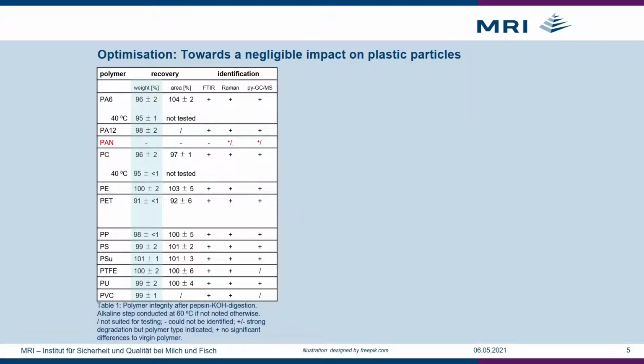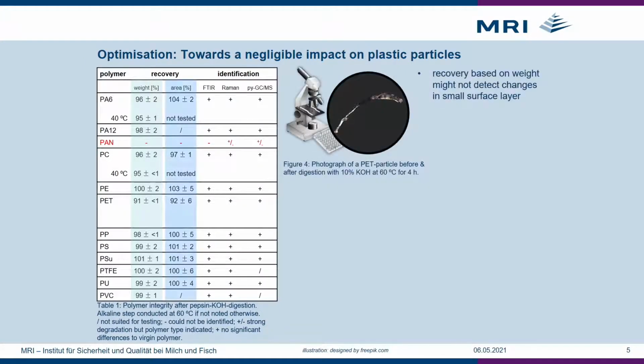First of all, we addressed polymer integrity, so we checked the recovery of polymer mass after enzymatic alkaline digestion. However, if changes occurred only in a small surface layer of a few micrometers, the weight recovery would not detect those changes, and loss of small particles would remain undetected.